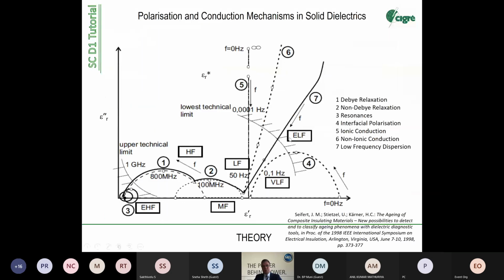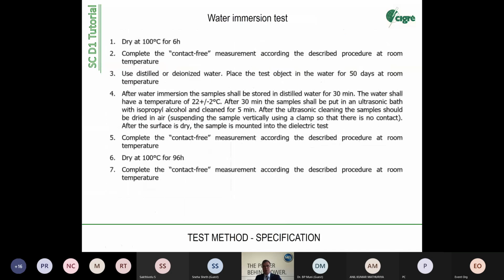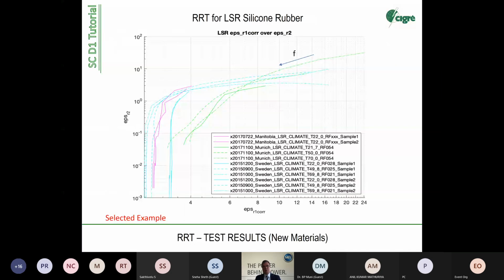So what you see in this curve is coming from here, from the lowest technical limit down to 50 Hertz or even a little bit more. So we don't go into kilohertz or megahertz area, but we are somewhere here in this falling branch of the so-called low frequency dispersion curve. I go back to the other one. So just to give you orientation where we are. So it fits with the theory, and we are looking to the right signal, so to the right range. Because we are searching for interfaces, we are searching for ions, for molecules that are moving, for slow moving effects.